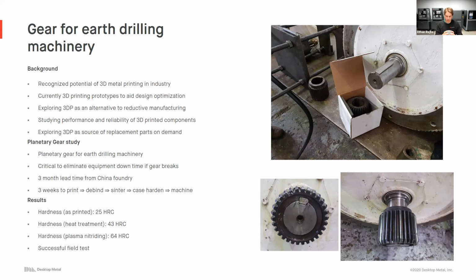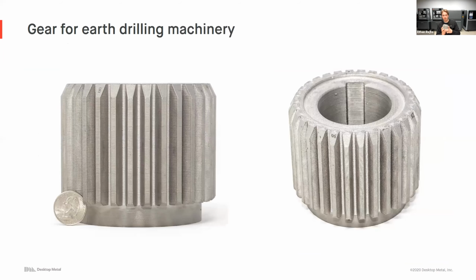You can see the results there on the bottom: after printing, they had about a 25 Rockwell. After that first heat treatment process, they got up to 43. And then after a plasma nitriding, which really helps to increase the hardness on the surface, all the way up to a 64. But it's a great example of a part that was originally cast, they needed a replacement. So what did they do? They went to their studio system and were able to produce a part going from 3 months down to just 3 weeks. This next part here is a thermostat housing.